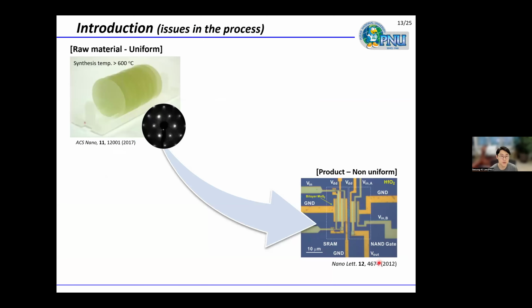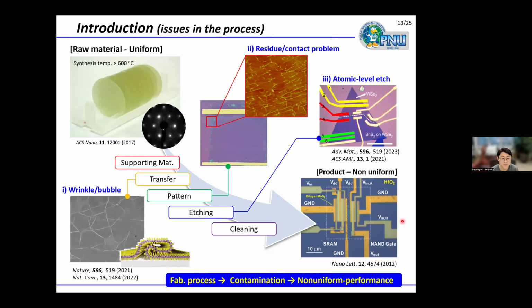Even now, most researchers rely on wet or dry transfer processes to fabricate 2D electronic devices. The challenge begins at the very first step of device fabrication. To build even a basic device such as this image, the 2D material should be separated from the mother wafer and then transferred onto the target substrate using a supporting layer. During this process, defects such as wrinkles and bubbles are formed at the interface. After transfer, patterning and etching are required to define the device structure. But these steps can leave unintended residue on the surface.